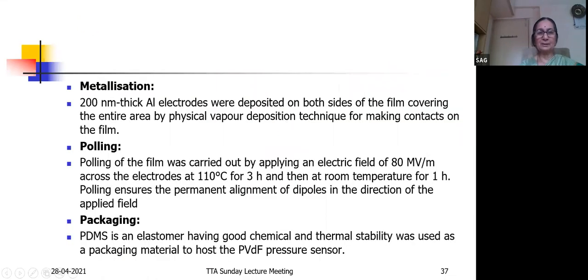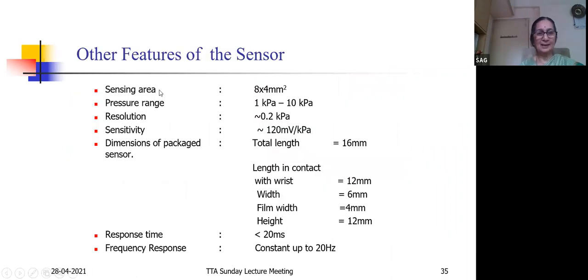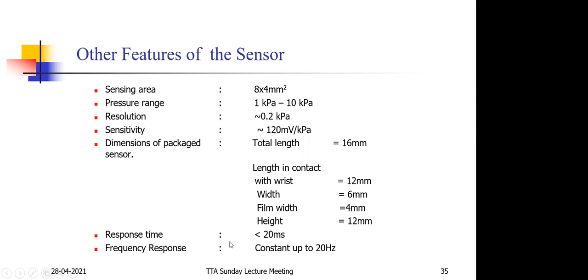That is required because the sensing area on the wrist is 8 by 4 millimeter square. Pressure range required is 1 kPa to 10 kPa. Resolution, these are the other sensor characteristics or features. Dimensions are, especially, total length is 16 millimeter, length in contact with the wrist, width in contact with the wrist, and therefore film width used and film height used. The response time and frequency response.